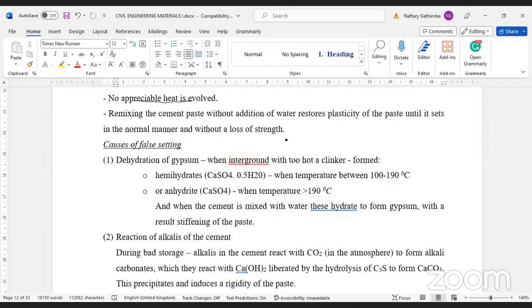So what happens is that the clinker is the end product from the production. You have the kiln, the rotary kiln. We have this pellet now, 3 to 25 millimeters in size, the clinker. And then we are adding gypsum. So this gypsum is hydrated, it needs to be hydrated.